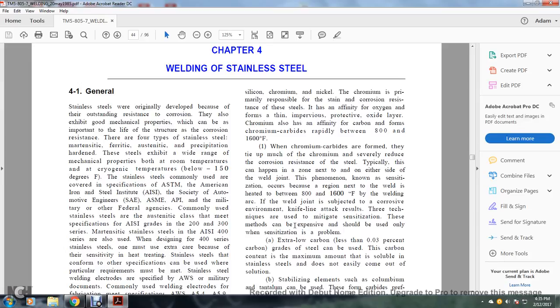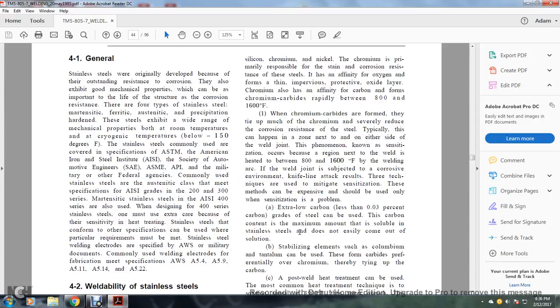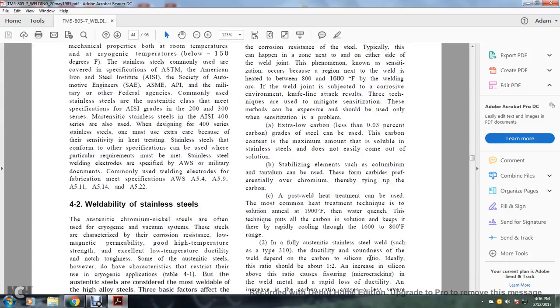There are three techniques used to mitigate sensitization. These methods are expensive and should be used only when sensitization is a problem. A. Extra low carbon grades, with less than 0.03% carbon, can be used. With the carbon content at this maximum amount, the carbon stays soluble in the stainless steel and does not easily come out of solution. B. Stabilizing elements such as columbium and tantalum can be used. The carbides form preferentially over the chromium, thereby tying up the carbon.